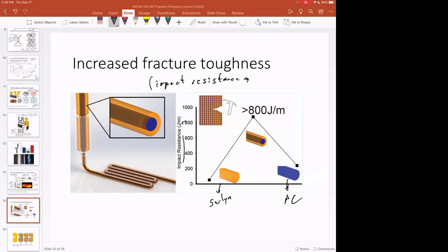Because of course, impact resistance is high rate. And fracture toughness, it turns out, is a low rate measurement in most cases. So if you want to be precise about it, they are slightly different measurements, but they're giving you similar information just as a function of time scale. But you see that the core shell now has higher impact resistance than either of the pure materials. And we might call this a composite effect, just like we saw with adding particles to polymers. And so we see that the mixture of materials has better properties than either of the pure materials. And so this is a clear indication of this composite effect.